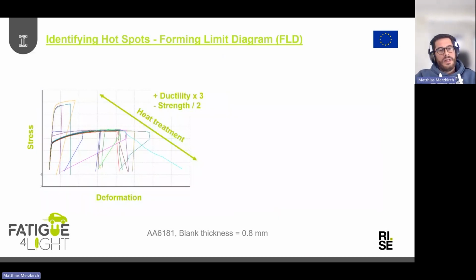And that was done with the heat treatment state. So here you see a bunch of stress strain curves determined from the material delivered from Profilglass in the heat treatment state T6. And what we did was basically killing the heat treatment state T6. That means high temperature, in the range of roughly 300 degrees C over a certain time, roughly 4 hours. And what is the aim? Well, to increase ductility. And as you can see here, a rough increase of the ductility by a factor of 3. Unfortunately, well, that was expected, a reduction in strength by 50%.